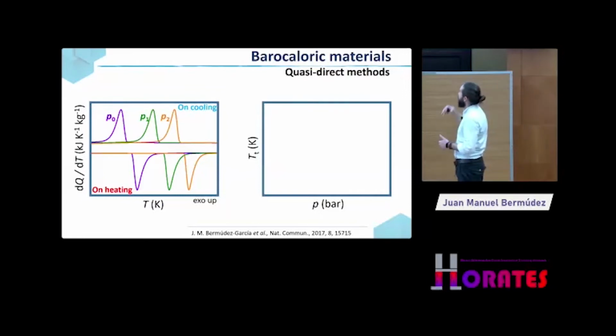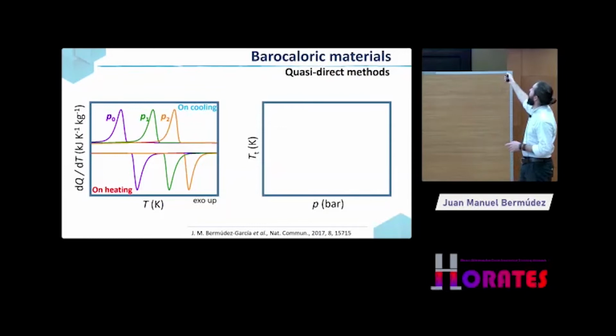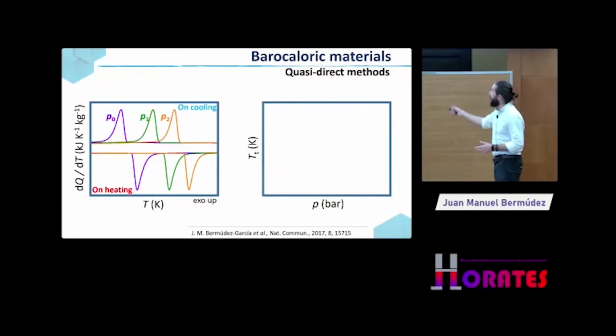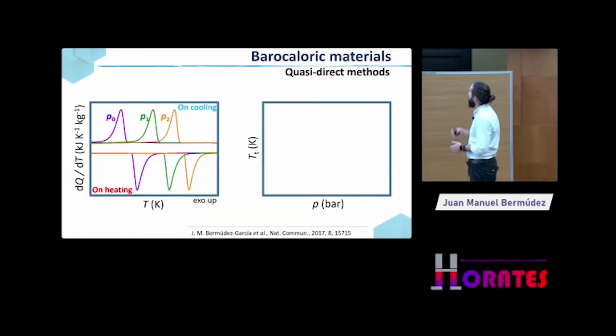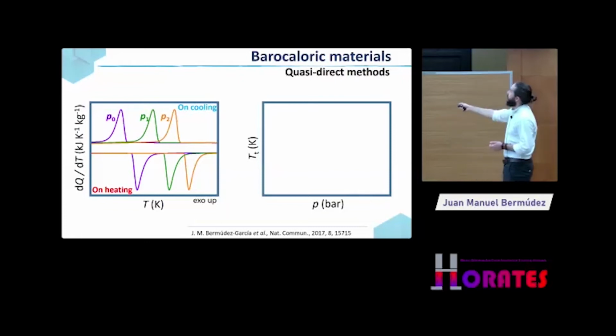What you can see from here, I didn't mention, but these are known as quasi-direct methods, because you're not measuring directly the enthalpy change associated with pressurization, but you are just calculating from those data. So the first thing that comes to your sight is that this phase transition in traditional barocaloric materials shifts towards higher temperatures when you increase the pressure, right? And from this data, you can build a phase diagram of temperature versus pressure, similar to the phase diagram that I showed you for the refrigerant gases. And on heating, which is gonna be the maximum of those peaks, and on cooling.